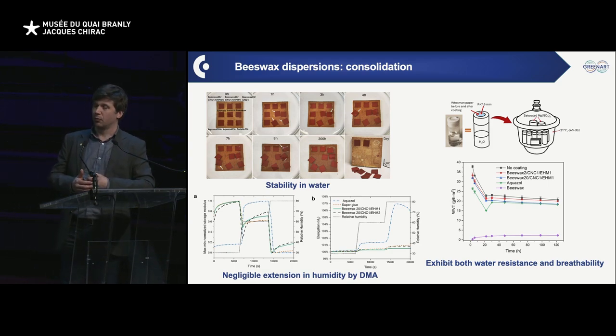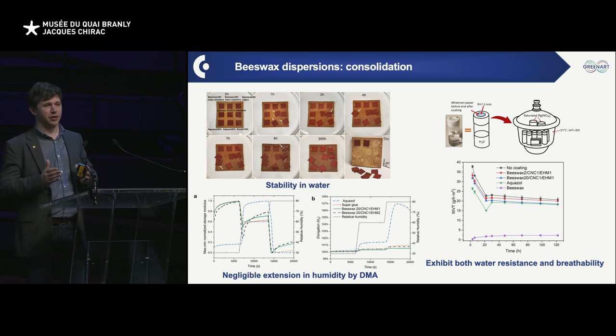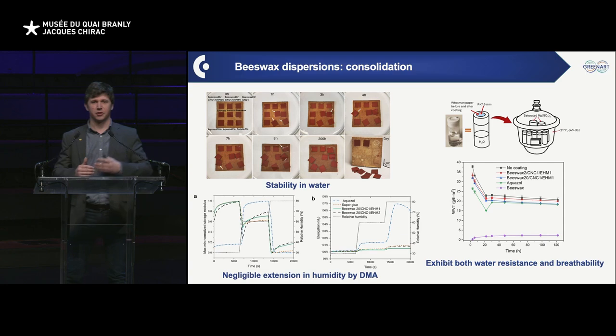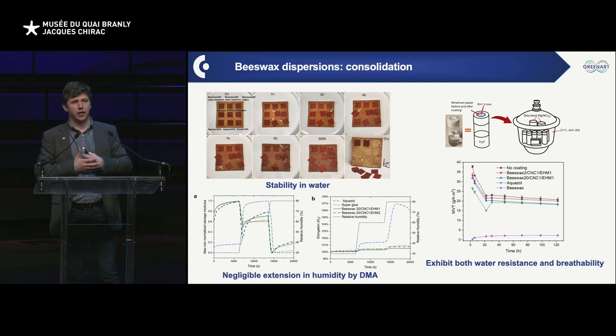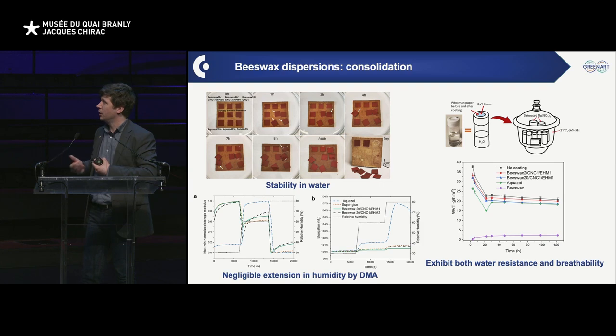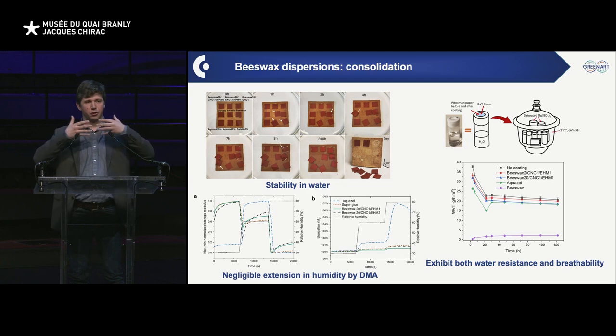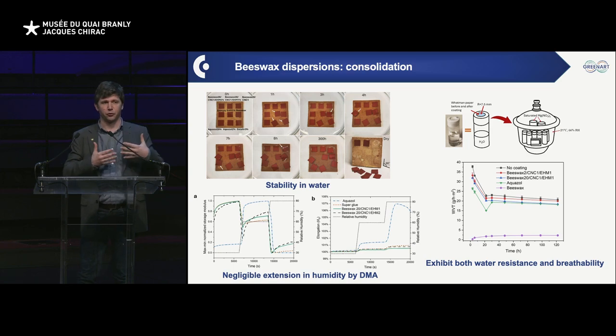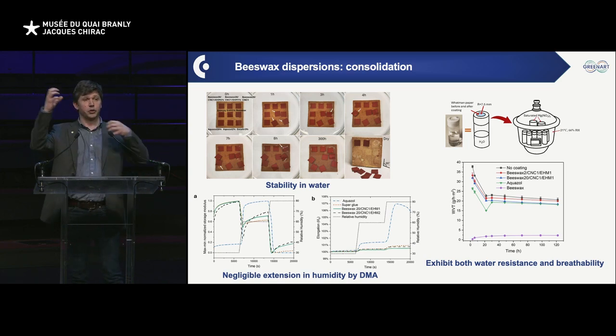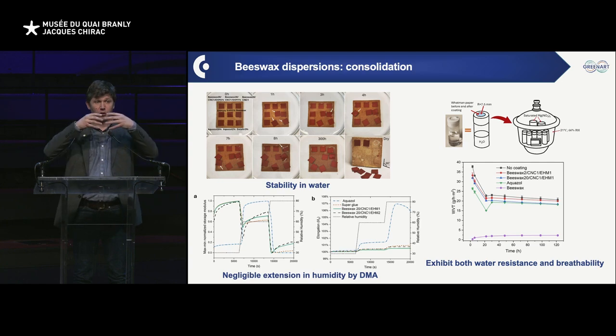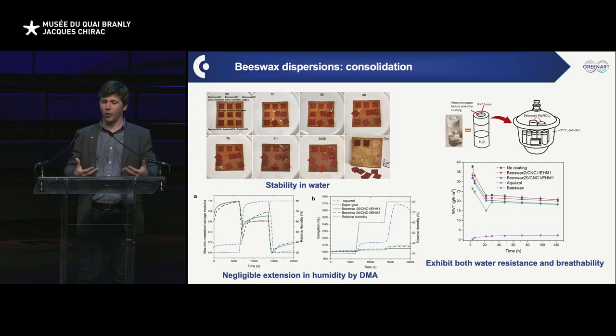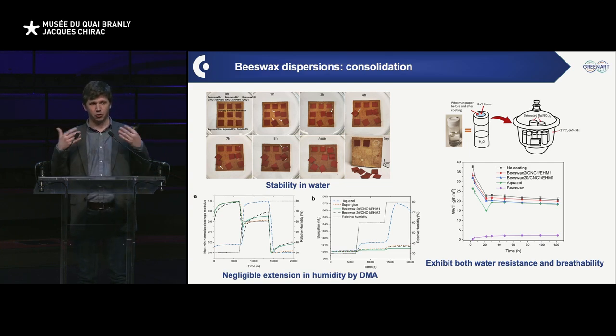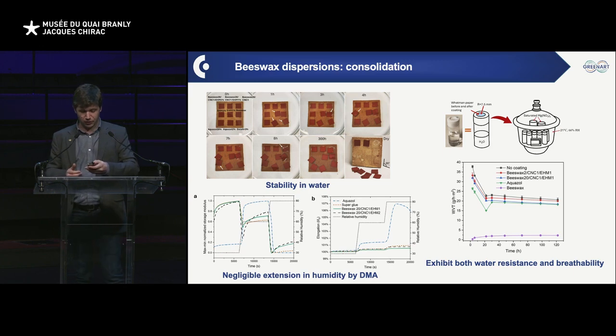Then we thought, okay, but humidity is not changing like night and day. It's not like you put it in water. There is variation, small variation of humidity daily, and that is important. So we conducted a DMA, and the conclusion of the DMA is that even though the system will adapt to changes of the plywood or the wood behind it, with time it will follow and it will not suffer from that. So the formulations, because of their colloidal nature, particulates that are not forming a film, are very well handling the variation of extension when we vary the humidity. And they are not much affected by the humidity.